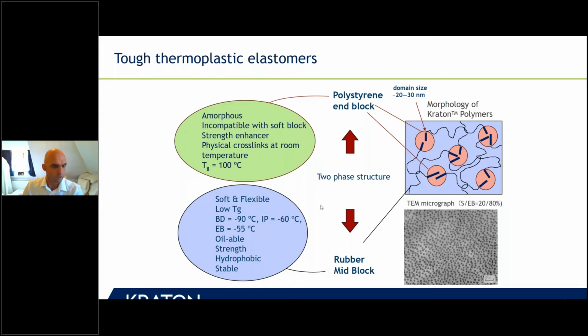Then there's the other phase of the soft segment, so the rubber midblocks. They are soft and flexible. They have low Tgs depending on the chemical nature. So if you have a butadiene-based midblock, it's roughly -90 degrees. Isoprene-based is about -60 degrees, and then you can hydrogenate them, and that's actually when we call our polymers specialty polymers. Those are the hydrogenated styrenic block polymers. Of course, they have the benefit of higher stability, both thermal, UV, and some other aspects, but you also increase the Tg a little bit.